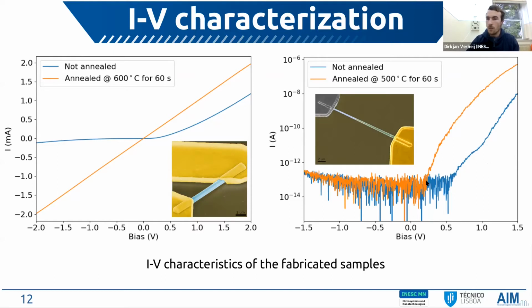So the forward bias current shows an increase, and also the threshold voltage at which the current starts to increase lowers. And this again means that we are lowering or even eliminating the potential barrier at the metal semiconductor interface. Then I also want to highlight the very low dark current we obtain. So in this case, lower than 1 picoampere, which is the resolution limit of our measurement equipment.